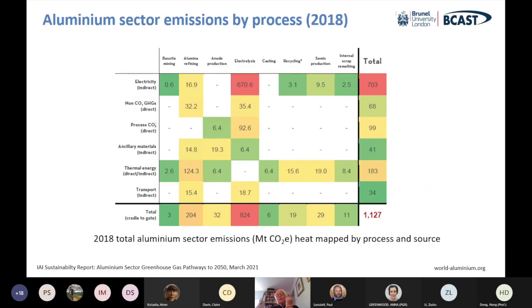And you can see what the real problem is with this sort of heat map, which again comes from the same report, which just shows just how much of the carbon intensity is due to the electrolysis going on during the primary production process. You can see that of the 1.1 billion tons of CO2 produced by the aluminium industry, you can see just how much of that is produced during the electrolysis stage, which is why there's so much